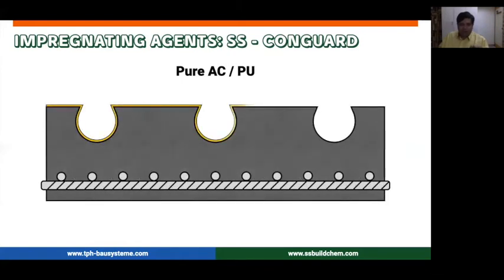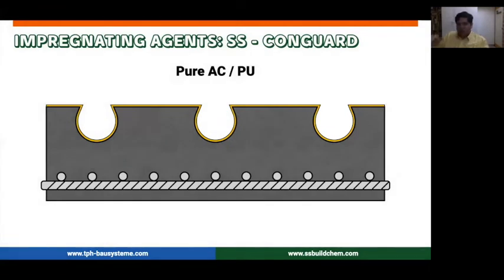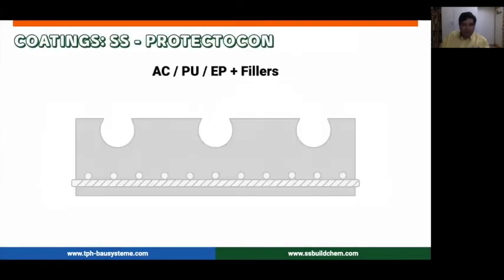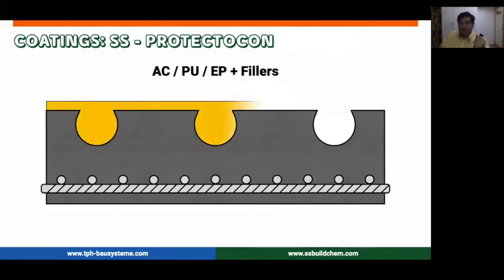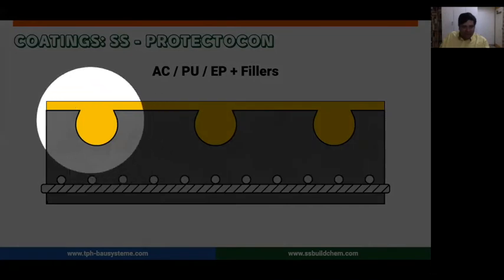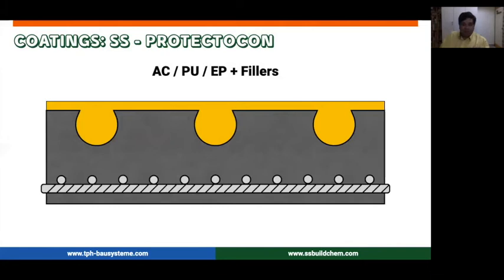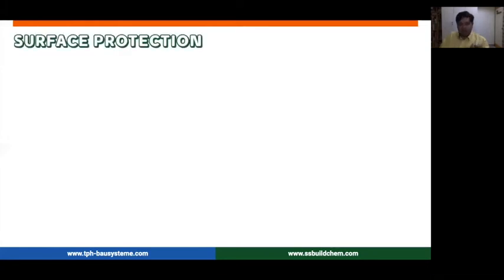Your impregnating agents or your primers, they very simply leave a barely thin coating on top, and it covers all the surface discontinuities. On top of this, you can put any coating that you choose. What a coating normally does is provide protection for your concrete. So it fills in all the surface imperfections, and on top of that leaves an additional layer, which acts as protection for the concrete system in general.